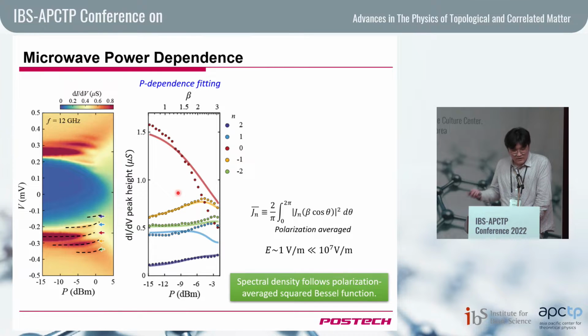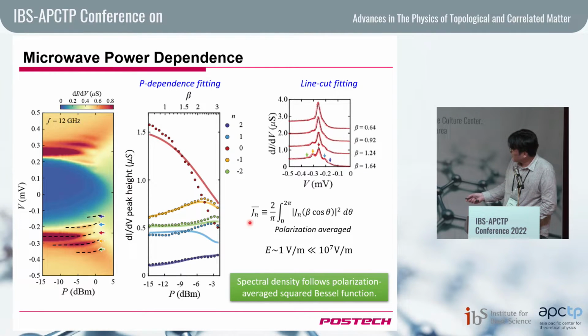Okay, and going further, in collaboration with Professor Gil-Ho Lee at the same university, and also one of his students, we were able to fit it with theory. So at least theory suggests that the spectral density of the nth Floquet state should follow the Bessel function of n squared here. But here, beta is the normalized strength that I described to you. It is given by electric field divided by frequency squared. And theta is the polarization angle. But because we think the microwave light was not polarized, we just average it out. And that gives us these theoretical lines as power dependence.